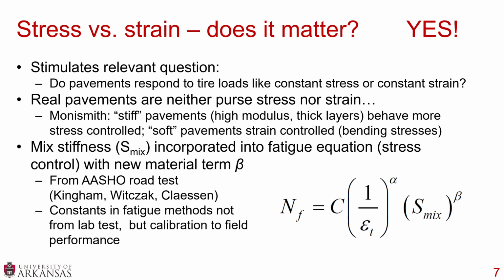Now, this is from the AASHTO road test. A lot of work that was done by Kingham, Witczak, and Claessen led to the development of this mix stiffness and also the new material term beta. And the constants in the fatigue methods are not from lab tests, but they're actually calibrated to field performance. And this is a very important distinction here. This means that we're taking the lab behavior and we are actually calibrating it through the material constants to field performance.